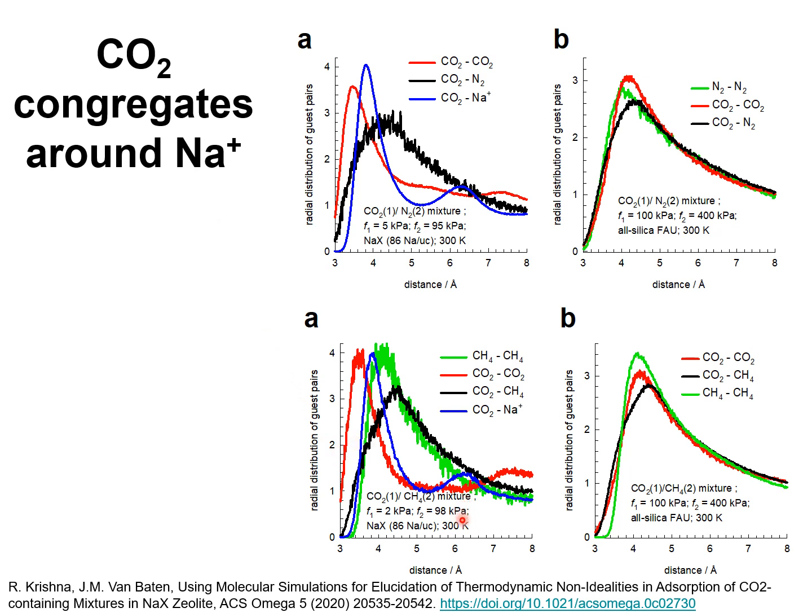And this explains the reason that the IAST, which assumes a uniform distribution of adsorbates, overestimates the adsorption selectivity.